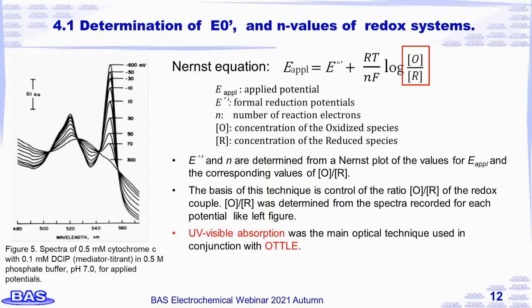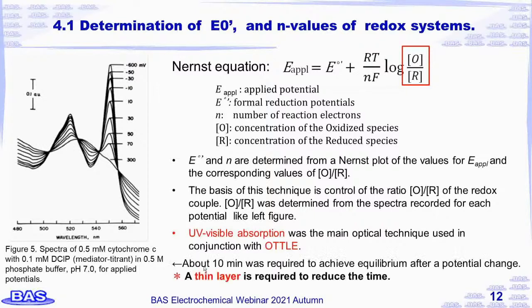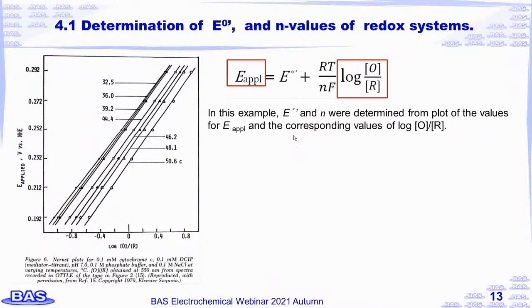Spectra for cytochrome c for a series of applied potentials are shown in Figure 5. The cytochrome is fully oxidized at 300 mV and fully reduced at minus 600 mV. In this case, about 10 minutes was required to achieve equilibrium after a potential change. Therefore, a thin layer is required to reduce the time. In this example, E and N are determined from a plot of the values of E_appl and the corresponding values of log O divided by R.